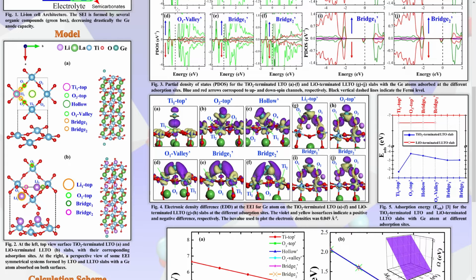Figure 4 shows the electronic density difference. It shows the charge transfer between the surface of the electrolyte and the absorbed germanium. The violet and yellow surfaces indicate a positive and negative difference respectively. From A to F, for the titanium dioxide termination case, after geometric optimization, the germanium atom moved to another absorption site except for the titanium top case.